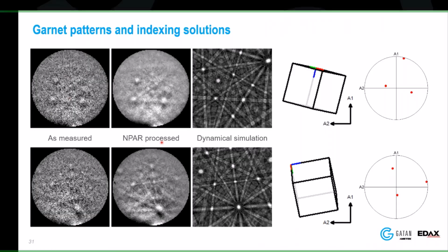This is one of those things where, if you're in the EDAX sphere, you know what NPAR is. We use by default a hex-based sampling grid, and I can tell you why. It's a couple of different reasons, but the main one is it allows us to look at our neighbors. This is what we call neighbor pattern averaging and reindexing. So NPAR lets me look at my nearest neighbors. If I have a hex grid, I have 6 nearest neighbors. And of those nearest neighbors, I can add all those patterns together to increase the signal-to-noise ratio. So instead of a pattern like this, I now have a pattern like this.